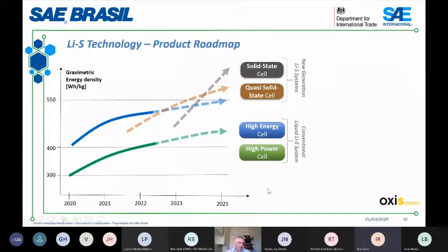And this will provide enormous improvement in the performance of the cells in terms of energy density. We are aiming to achieve 550 watt-hour per kilo at the beginning of 2023, and then reaching 600 watt-hour per kilo. And then with the solid state cells, we will achieve higher levels of gravimetric energy density, together with the cyclability and the temperature range. We're expecting to achieve 60 to 70 degrees of temperature.